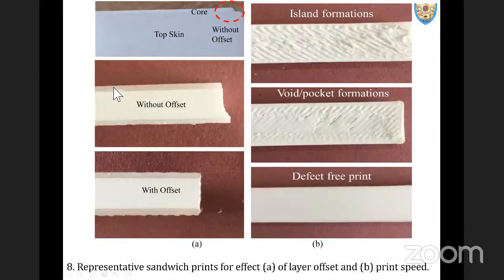In addition, though the layer offsetting is a machine dependent parameter, we need to keep an eye on this. This is nothing but the distance between the two nozzles. If the machine is being used very often, we need to look at this offset. If you don't look at that, there will be an offset like this. This offsetting is a machine dependent parameter, which you need to look at, set and compensate. And if you compensate, your samples will come good.